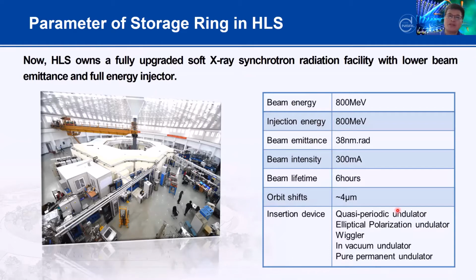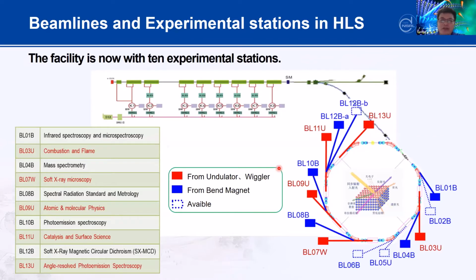As you can see, this is the parameter table for the storage ring in HLS, which I already mentioned. The beam energy is about 800 MeV, the injection energy is about 800 MeV, and the beam emittance is about 38 nanometer rad. The beam intensity is about 300 milliamp, and the beam lifetime is about 6 hours. The orbital shift is about 4 microns. So this is our storage ring parameter. And with this storage ring, we have the beamlines and experimental stations. At this moment, we run 10. As you can see, the red color is from the undulator and wiggler, and the blue color is from the bending magnet. Basically, we have 5 undulator stations and 5 bending magnet stations.